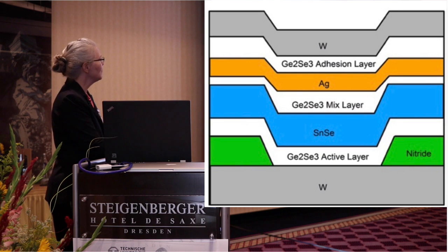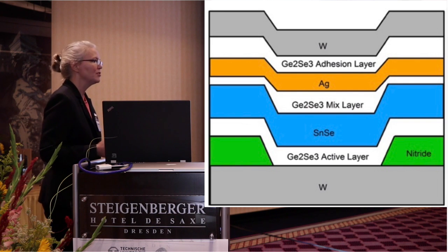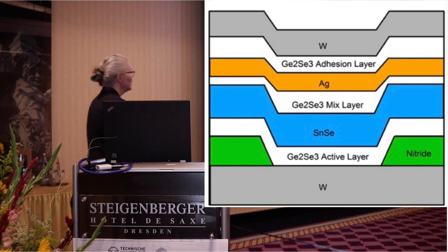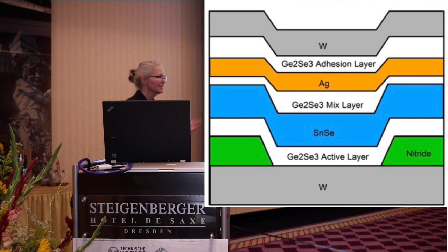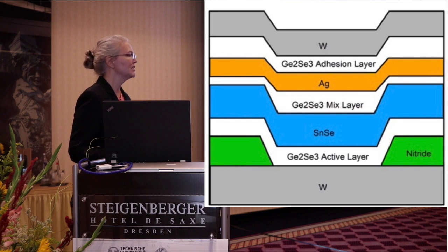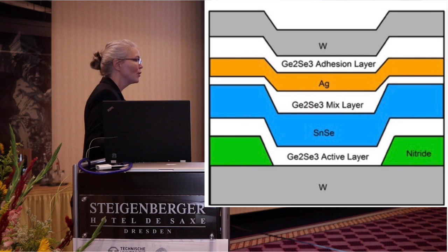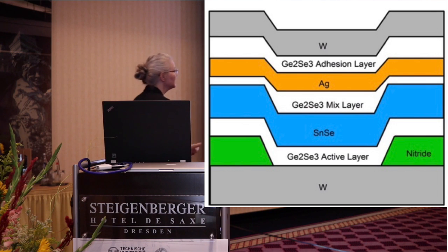And the other easy thing about this is you can put all of these layers down in one step in a fabrication tool, a sputter tool. So even the top electrode, it's all done at once. It's simple, no photolithography, it's very easy and very fast. And we can do it at a university fabrication lab like Boise State's, getting undergrads to do the fabrication on devices, and we always have more than 95% yield. It's a really good, simple process.